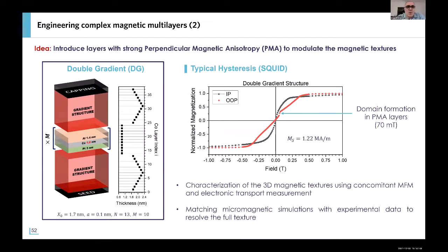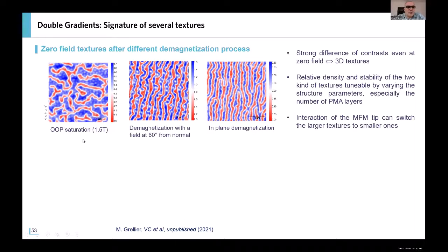But then we can go beyond and prepare more complex stackings, more complex heterostructures, by using two of these gradient multilayer blocks separated by a multilayer with large perpendicular magnetic anisotropy. And then look at what happens. These are very recent images that we obtained by MFM. You see that after the out-of-plane saturation and going back to small field or zero field, we clearly have two contrasts. This is more visible here, where we have a demagnetization with an angle. We have these stripes in red, and then in between the stripes we have this white structure, which demonstrates that we have two types of magnetic texture in the multilayers.